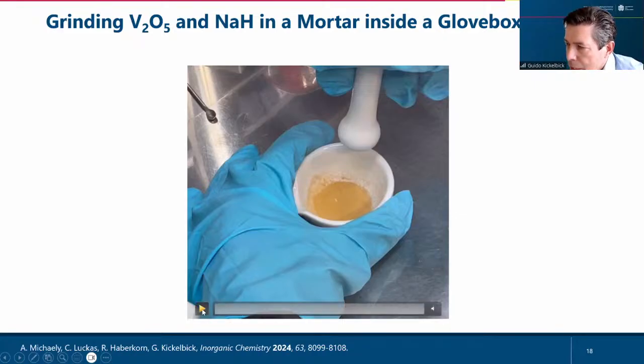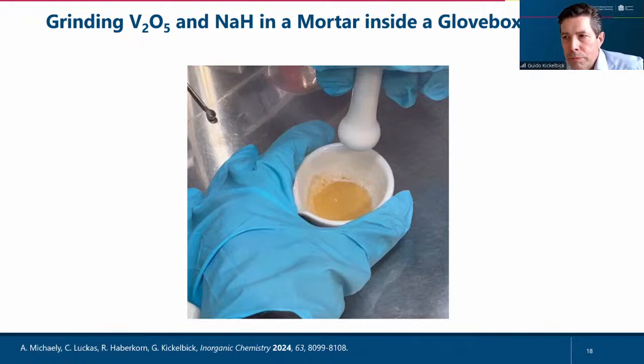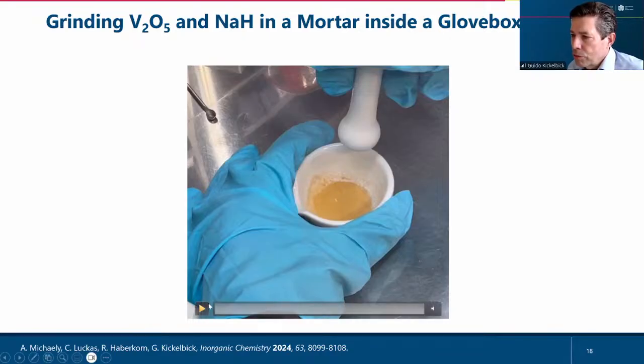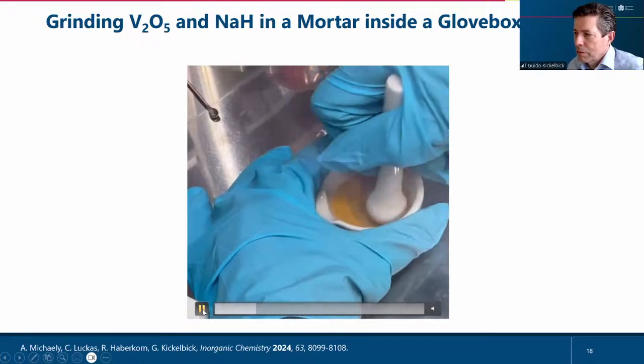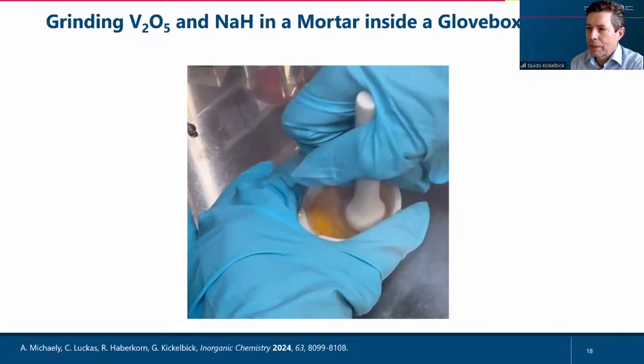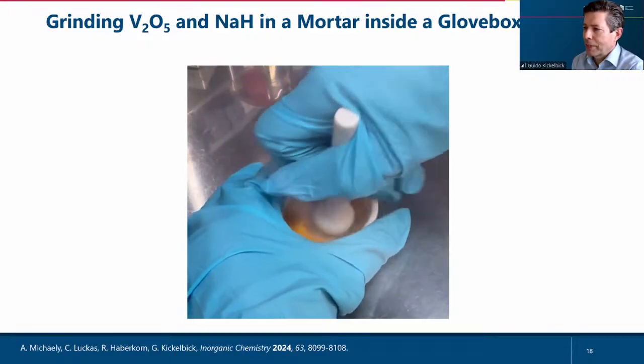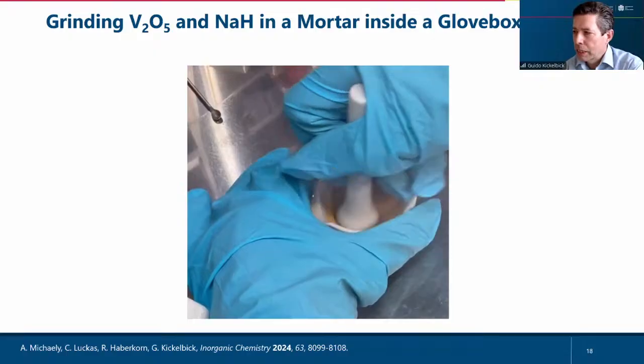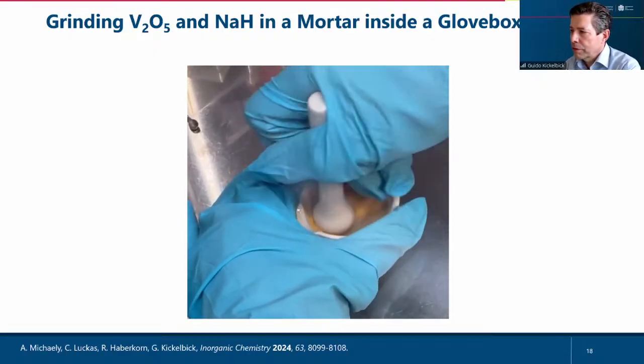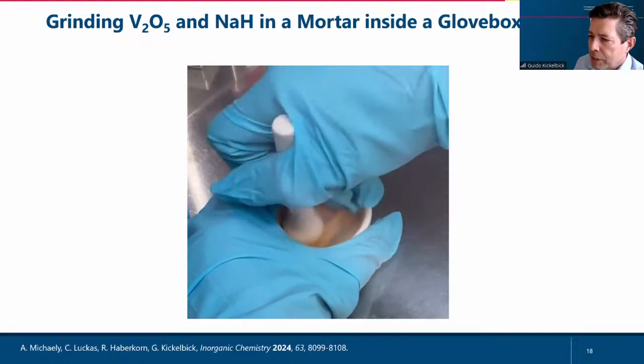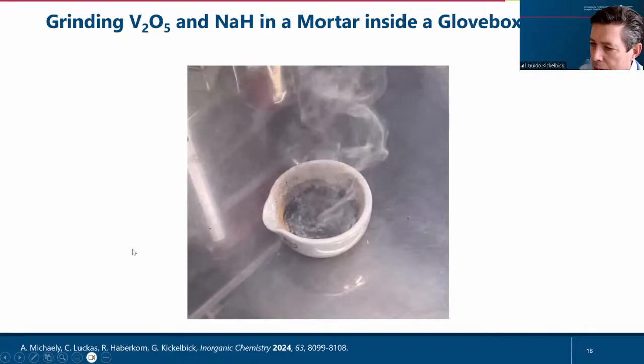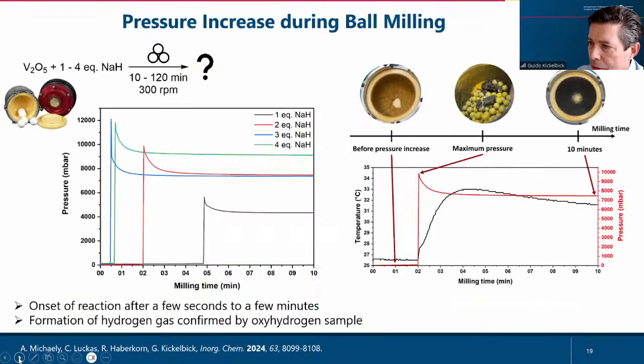So this is a mixture of vanadium 5 oxide and sodium hydride in a glove box under argon. And the student treated that just by mortar and pestle, so it's under argon atmosphere. And you see that this is a very vigorous reaction. So the question was, how can this happen? You have really a highly exothermic reaction in this reduction.